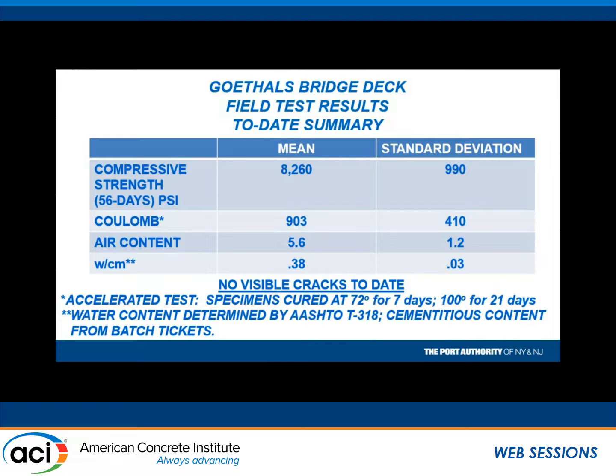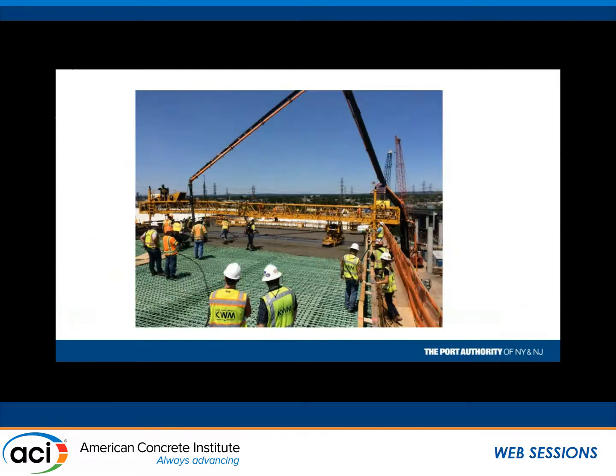But that's how good this mix turned out. And I think that's a success story. Low diffusion characteristics, no cracking, and the strength went along for the ride. We have too much emphasis here on strength and not the properties that really matter. Whether that concrete is 8,000 or 5,000, nobody would miss it. But if you've got a lot of cracks in it, you're going to have poor durability, poor service life in that concrete. And of course, if the diffusion is high, that's not going to work either.